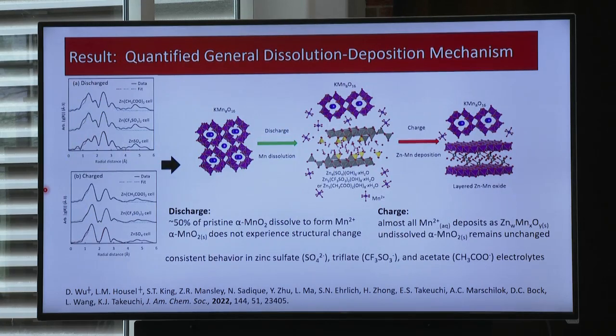So when we look at the combined mechanism, what we're seeing overall is the transformation of the cathode material into zinc manganese oxide and the precipitated ZHS phase. On charge, we recovered manganese oxide in two different phases. Some of the original tunnel structure remains, but then we do recover a layered structure as the charge progresses, because much of the dissolved material doesn't redeposit in the same phase that it was originally formed. It redeposits in a new phase structure.